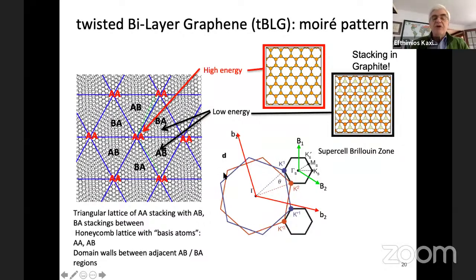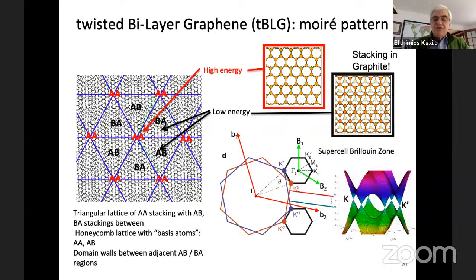And this is now the reciprocal space. You have two hexagons, one from each layer, the red and the blue, and these correspond to the entire layer. But because now you have this superperiodic arrangement, the Moiré pattern, you form smaller hexagons in reciprocal space, which corresponds to the supercell, the larger periodicity. And everything now that we need to understand has to do with this smaller area in reciprocal space, the supercell Brillouin zone. And from each layer of graphene, you get these Dirac cones, one set of Dirac cones from the blue layer, another one from the red layer. So for the black hexagon, the supercell that corresponds to the Moiré pattern, you have Dirac cones at each one of these corners from the two different layers.